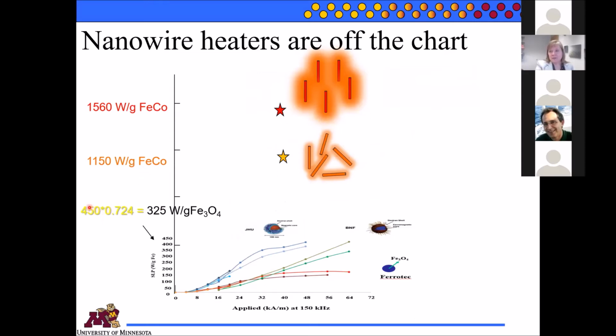Now, in reality, when you put this 450, if you're doing watts per gram iron, you actually have more grams of iron oxide in that same particle. These aren't iron particles, they're iron oxide particles. So if you really compare watts per particle mass, then you're talking more about 325 watts per gram particle. And for iron cobalt, if we have randomized particles, we see some very high 1150 watts per gram at 40 kiloamp per meter and 150 kilohertz.